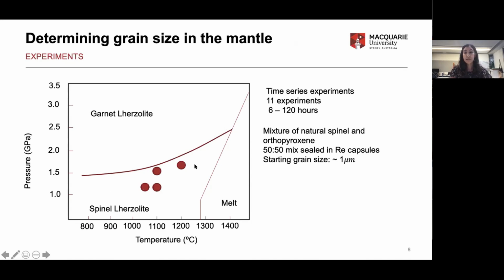This pressure temperature space was chosen to reflect where the majority of spinel peridotite xenoliths are often found or thought to have come from. So just to repeat, my mixture was a natural spinel and orthopyroxene, 50-50 mixture, which was sealed in rhenium capsules, and I ensured I had that very small grain size initially.